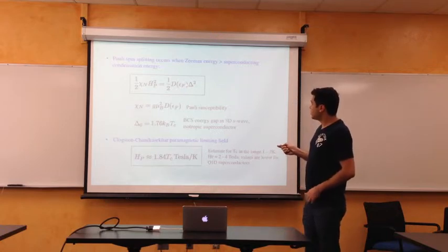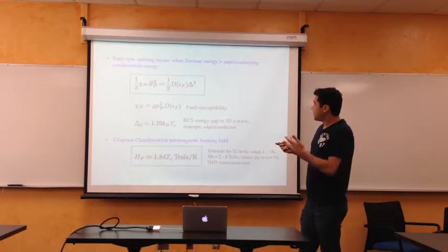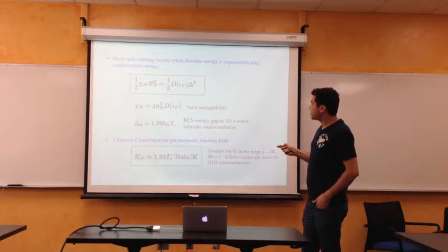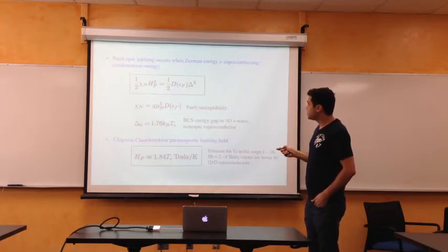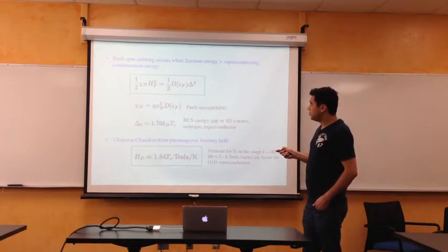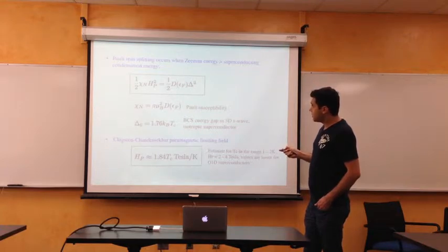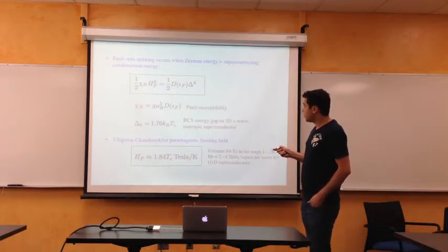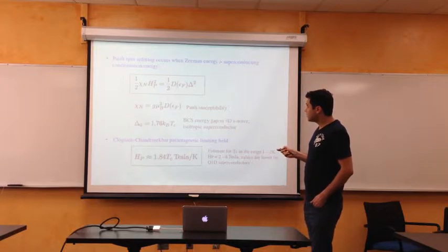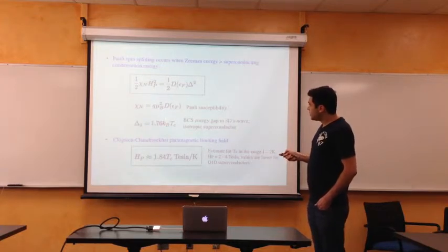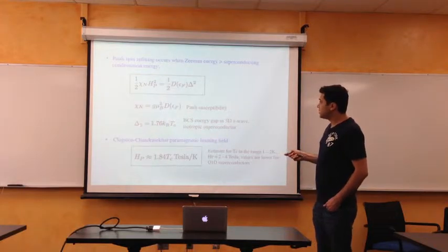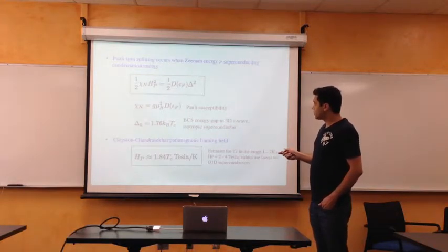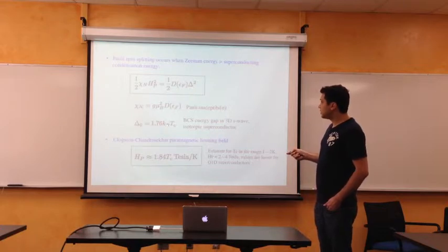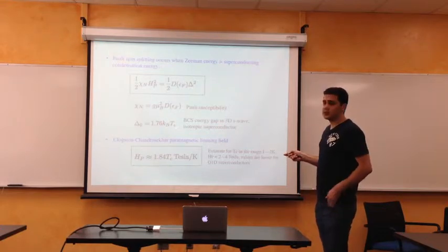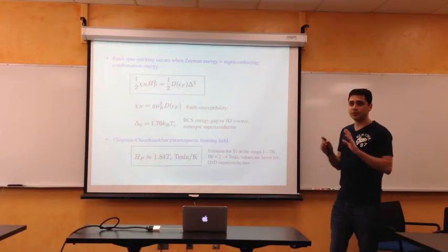So when we set them equal to each other, we can numerically—in fact algebraically—extract this paramagnetic limiting magnetic field. Here chi n is just the normal metallic state Pauli susceptibility, which has this electron g-factor, about 2, Bohr magneton, and the density of states at the Fermi level. And delta 0 here has been set to the BCS value, a well-known result: it's 1.76 kB Tc, where Tc is just the superconducting transition temperature in zero field.